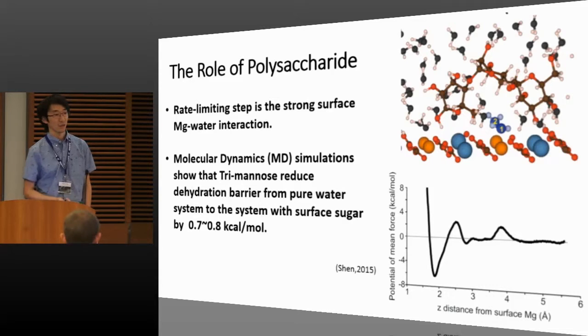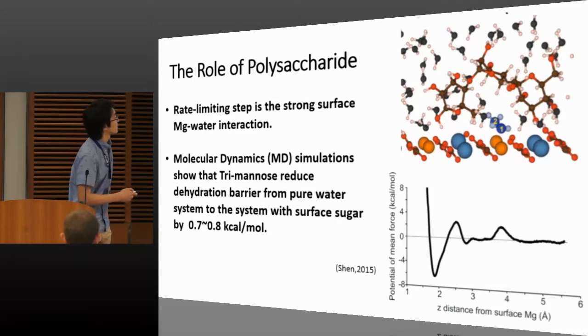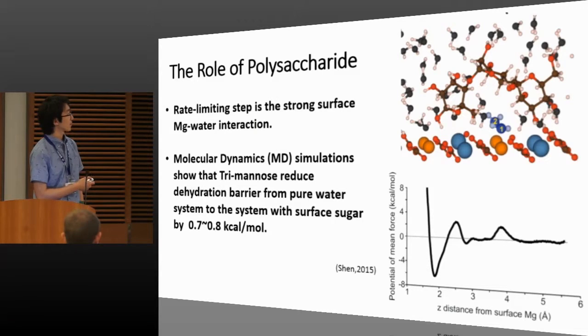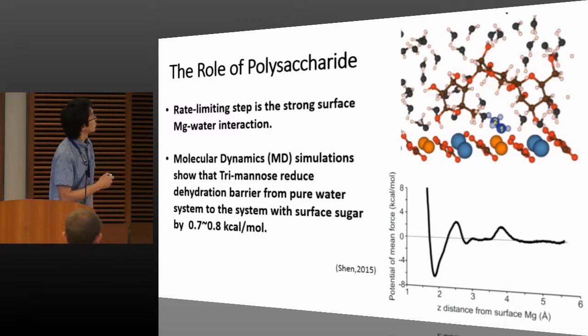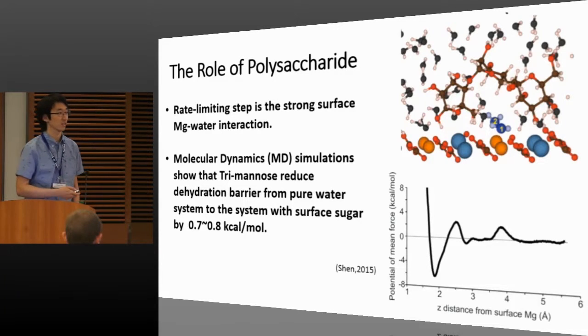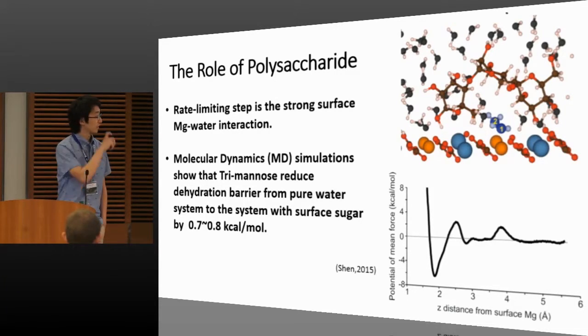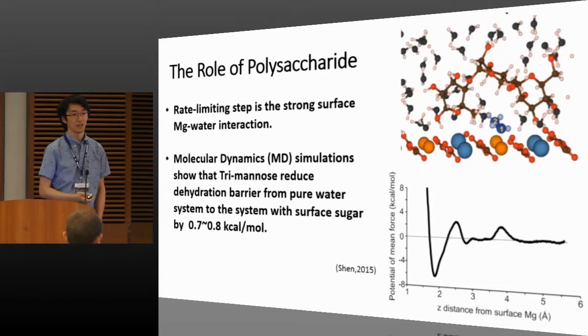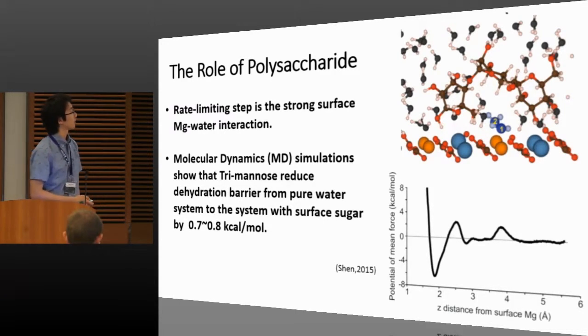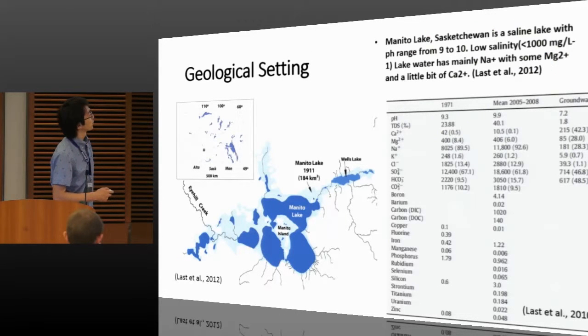But how does it exactly work? One of our PhD students tried to use molecular dynamics to simulate the trimannose. That's the only one we work on right now, to run the modeling on how much the sugar helped to weaken the bond between water and magnesium. And it turns out that it lowered the bonding energy by about 0.7 to 0.8 kilocalories per mole. That's pretty significant. So it turns out that sugar is really helping the magnesium to get into the crystal lattice to form dolomite. So now we move to my study.